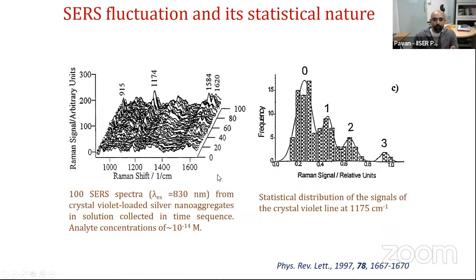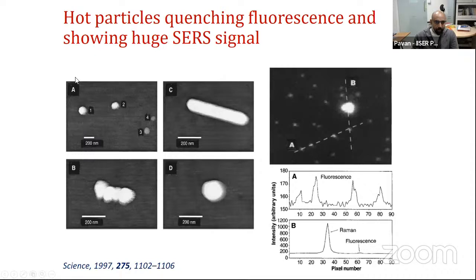Simultaneously, at the same time, when this experiment was published, there was another very famous paper in Science where people identified that individual nanostructures actually can quench fluorescence and result in very large Raman scattering enhancement. So one of the important messages from this experiment is, if you consider single nanostructures where you have molecules adsorbed to these kind of nanostructures, the fluorescence is much less compared to the Raman scattering signal. Okay, this is one of the prototypical examples of surface enhanced Raman scattering, which tells you that the cross section of the interaction for SERS is much higher than even the fluorescence signal. So it's an extremely efficient optical process. Therefore, it is used to study single molecule fluctuations in significant detail.